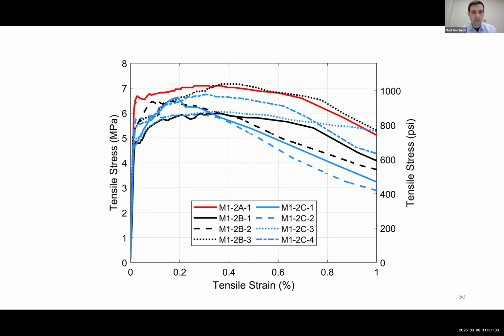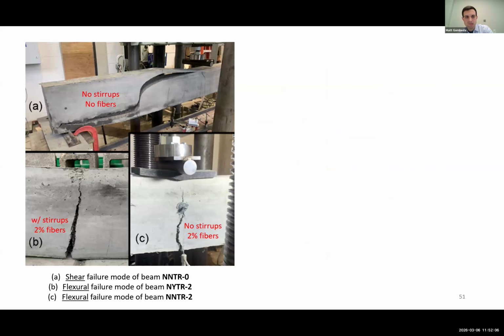And then here's a plot of the tensile stress versus strain across specimens that had the same mix design, but they were done from different batches, again, with the goal of demonstrating consistency and reproducibility in mixing them many times. So we saw pretty consistent trends of our tensile stress strain curve. And this one's only plotted up to 1% tensile strain, which is pretty good. Much higher remaining stress that you'd have versus a normal concrete, obviously, and thanks in large part to the steel fibers. And then we made some beam specimens with these mixes.